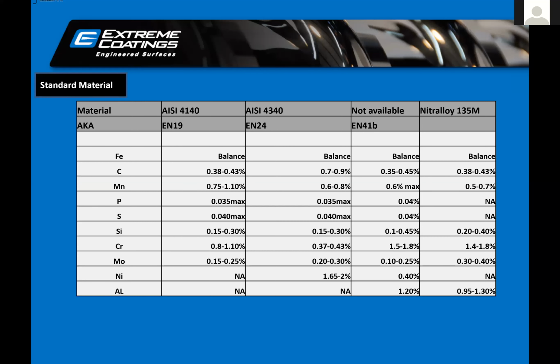And sometimes you may wonder why one screw maker gives a very cheap cost for the screw barrel, while other screw makers give a much higher cost for the same screw barrels. This is because of the material itself. EN41B is almost 2 times as costly as EN19, but the chemistry is very different. The steel may look the same, the hardness initially looks the same, but the steel chemistry is not the same. EN24 is better than EN19, and EN41 is better than 24. Nitralloy 135M is a specific steel used for nitriding, so it is even better than that.